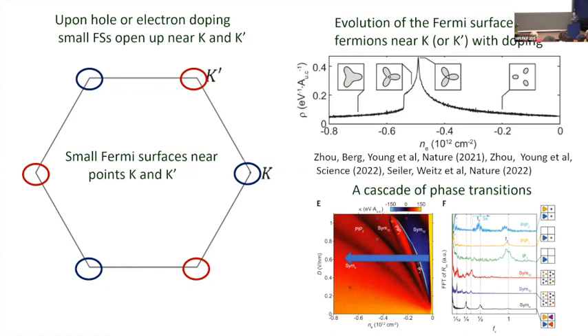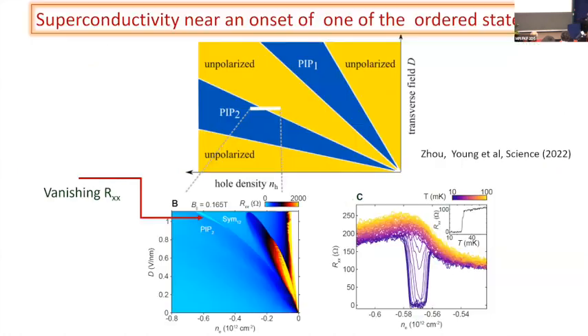When experiments were done, they did find a sequence of transitions. Taking a particular displacement field and going from charge neutrality towards doping into the conduction or valence bands, you see that the state of the system changes. This is reflected in quantum oscillations showing how Fermi surfaces change. Similar to twisted bilayer graphene, you go from a disordered state to ordered states and back, seeing different orders appearing one after the other.